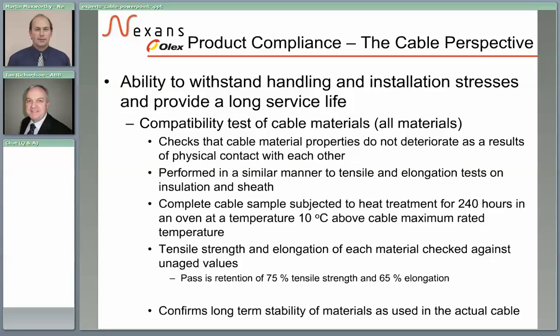Compatibility of cable materials is confirmed by subjecting a cable sample with all of the layers intact to a heat treatment of about 240 hours in an oven at a temperature 10 degrees above the maximum operating temperature. And then you recheck the tensile strength and elongation of each of the non-metallic materials again, and you compare them against the unaged values. The minimum pass criteria is that they have to retain at least 75% tensile strength and 65% elongation compared to the unaged values.